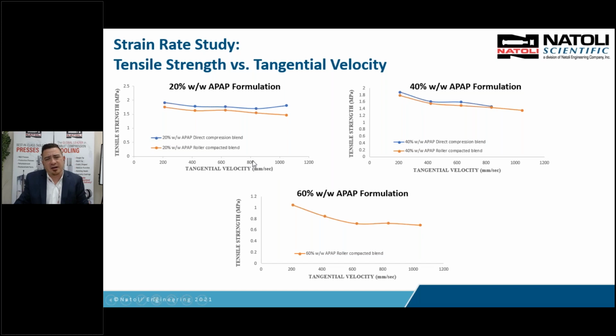Some are running at 600 to 800 millimeters per second. They're running at slow speed. But the larger your turret gets, or pitch circle, the higher that velocity is going to be at a constant RPM.